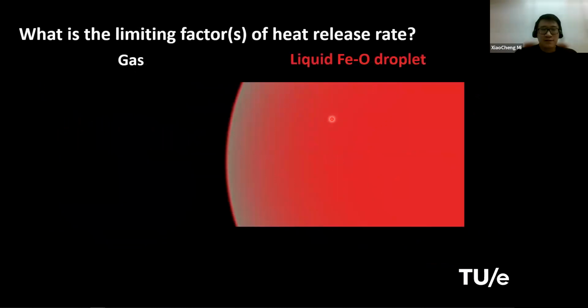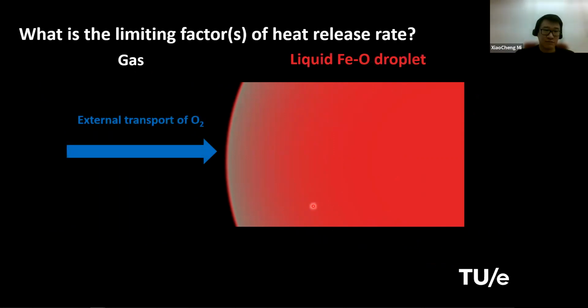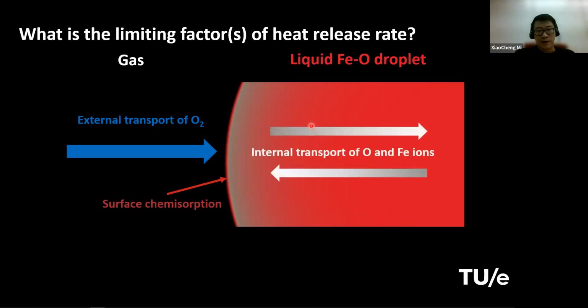And what could be the possible limiting factors that control the liquid phase oxidation? One thing is still the external transport of oxygen molecules from the bulk gas to the surface of the particle. The other is the surface chemisorption, like how much of the oxygen molecules that reach the particle surface can be absorbed as ions into the particle. And also the internal transport of Fe and O ions could be a rate limiting factor.